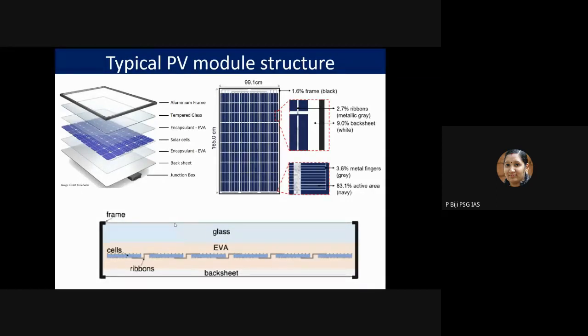The encapsulation basically protects the solar cells and the interconnects from the harsh outdoor environment throughout the module's technical lifetime. For example, solar cells are reported to have a lifetime of around 20, 25 or 30 years. So throughout this technical lifetime period, it has to be protected from the outdoor environment. That is the main purpose of this encapsulation. The main aim of this encapsulation step is to interconnect the solar cells by soldering and package them into a weatherproof structure. This step offers both electrical isolation as well as protection from the environmental damage in which they operate, for example moisture, rain, snow, dust, or some kind of mechanical shock. The most important stage of this encapsulation is the thermal treatment of the thermosensitive polymer resin.